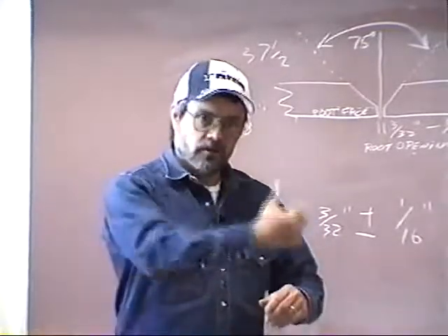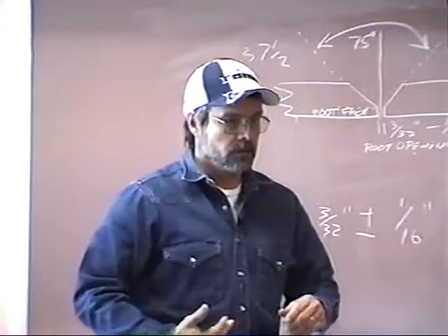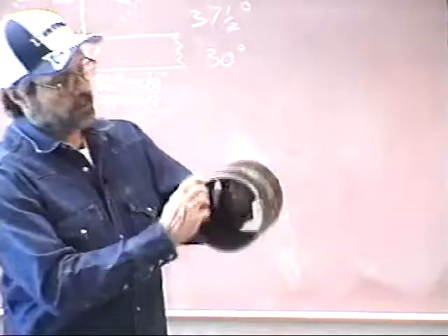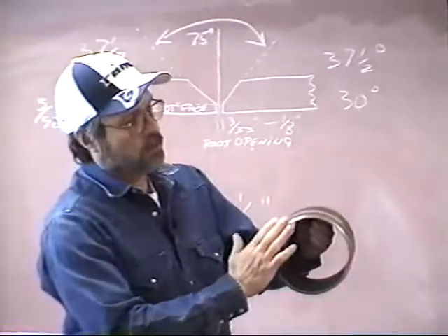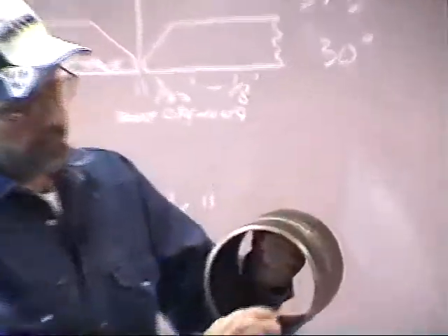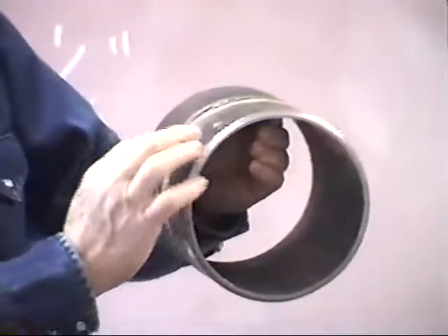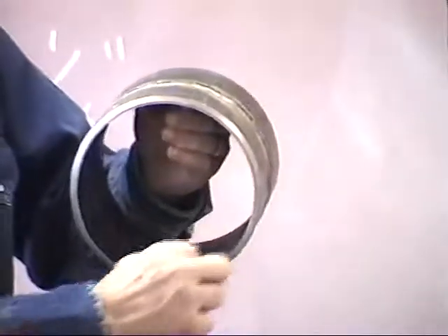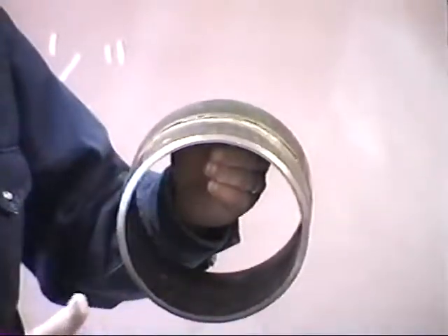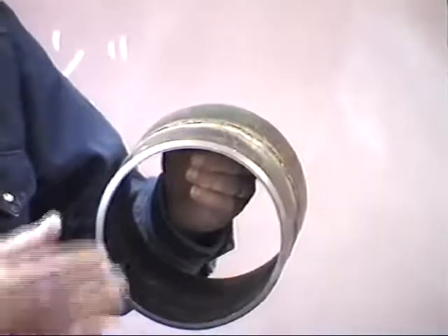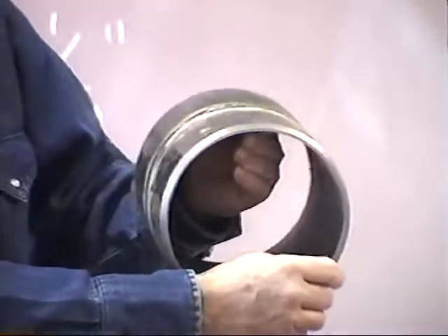Of course, you're going to get some carburizing on the pipe nipples from making that kind of a cut. They're going to carburize up, and you're going to want to clean that all off with a grinder. You're going to want to go around the inside with the grinder, or preferably a cup stone. And if one's not available, use a file and clean the mill scale and rust away from the inside.